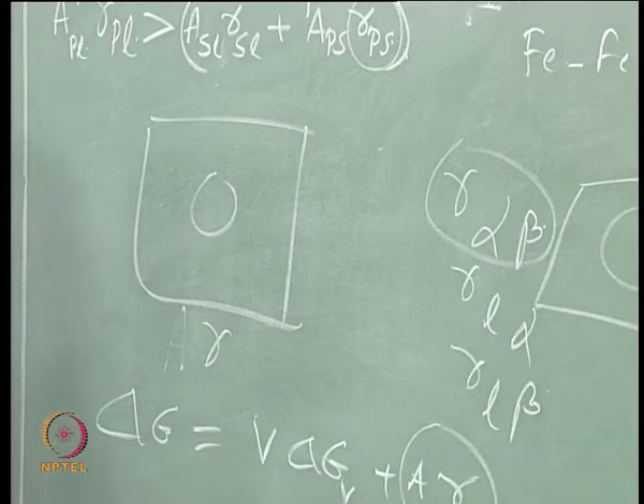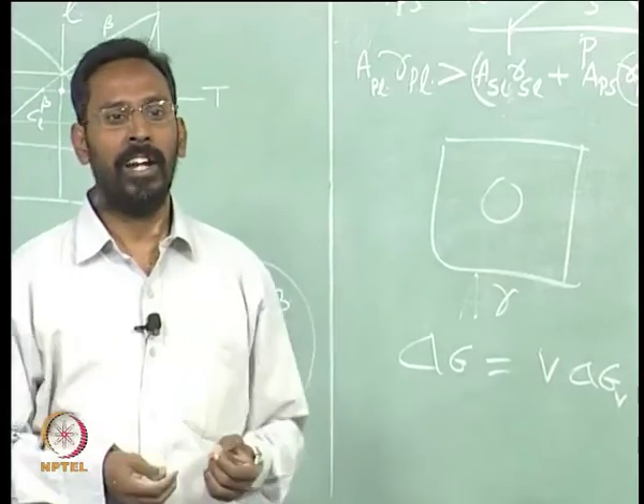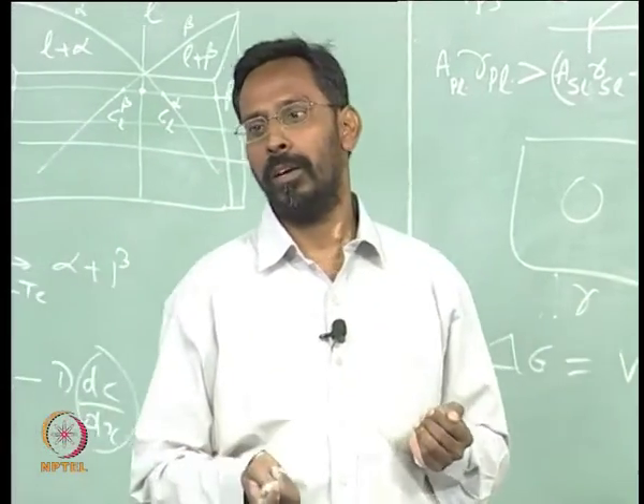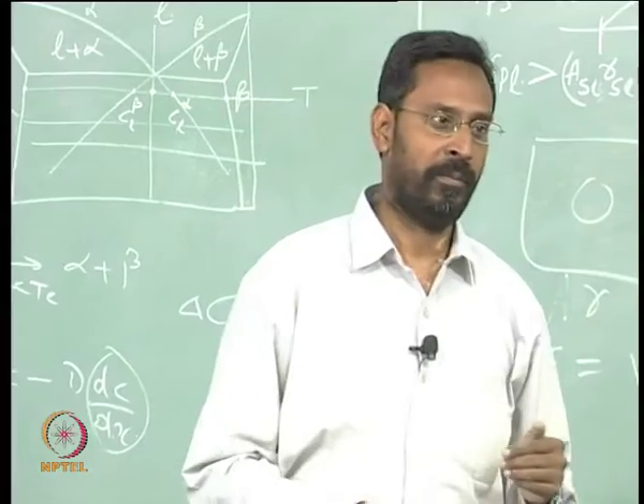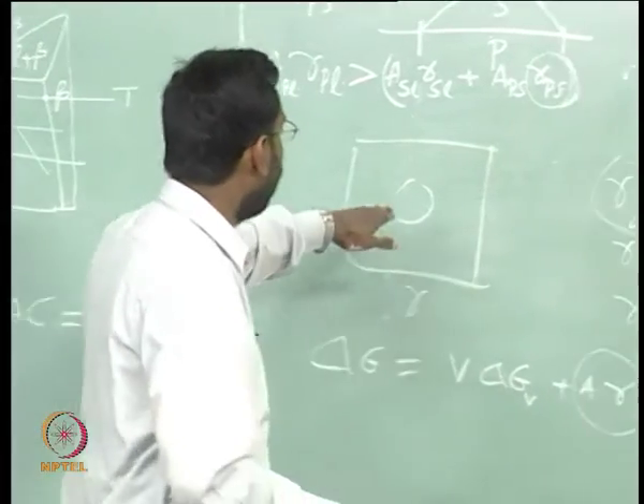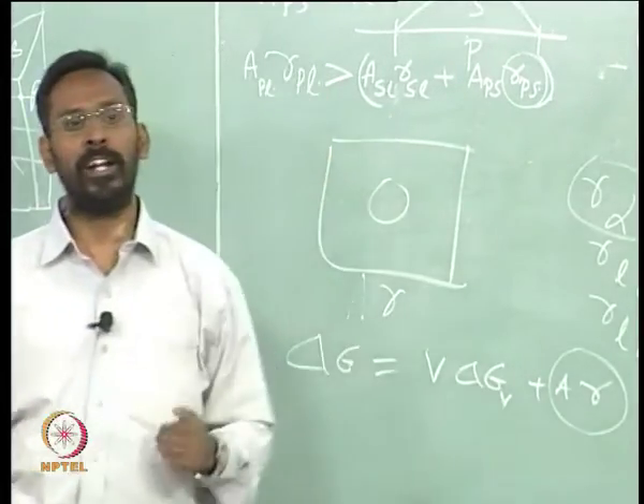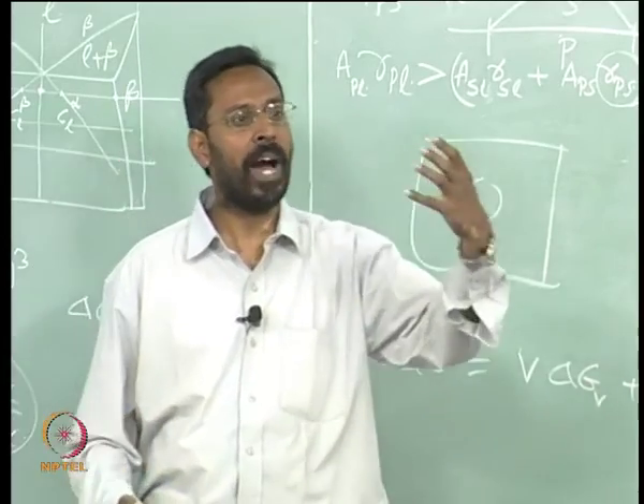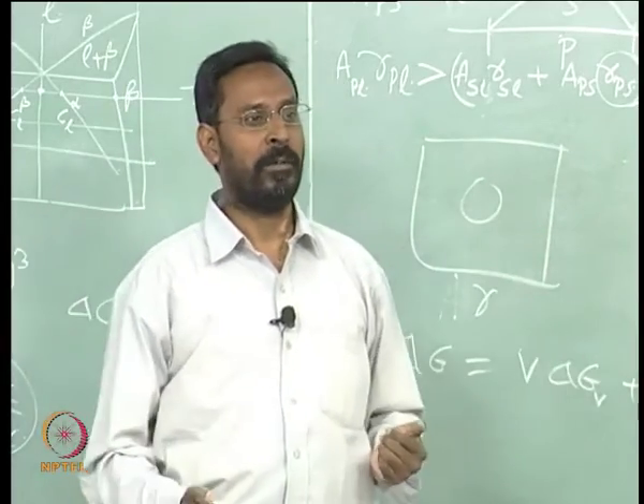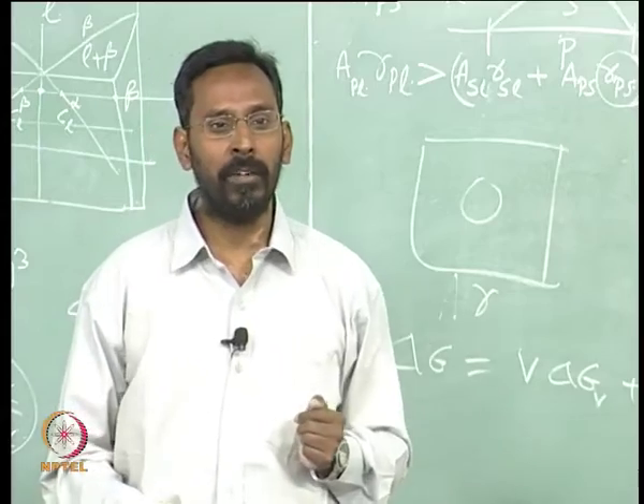It can be alpha particles, needles, or plates, depending on growth conditions and the structure of alpha. For example, cementite appears as particles in ledeburite, whereas in the aluminum-silicon eutectic, the silicon appears as needles.